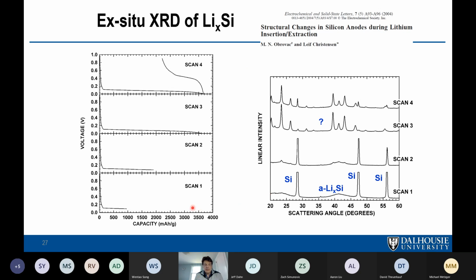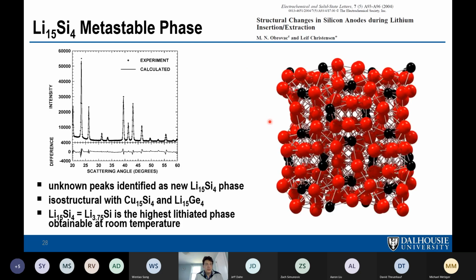And so this is ex situ X-rays. In scan 1, we stopped the cell here and we took an X-ray, and scan 2 and so on. In scan 1, we see silicon peaks, but then we saw amorphous silicon. And then we saw another phase growing out of the amorphous silicon when we got down to low voltage. And that phase didn't match with any known phase.